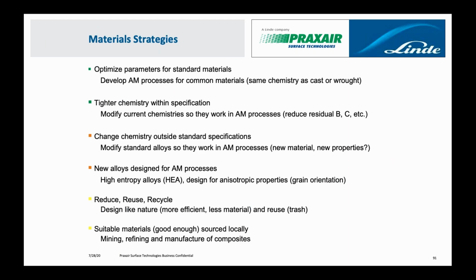So as a recap, where we've been, what we're doing now, and where we can go in the future. For a lot of these additive manufacturing processes, they've taken advantage so far of the materials that were already being used. And that was important in aerospace because these materials have a long history. They have certain properties. They have specifications. So there's a lot of work that's been done to print parts where the materials and the microstructure, so the properties, are the same as cast or wrought materials. And people have been very successful. And things like Inconel 718 alloy, that composition is very strong. It prints very well. It can easily be made into powder.